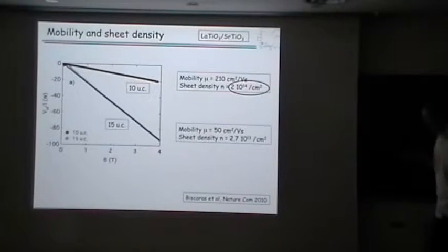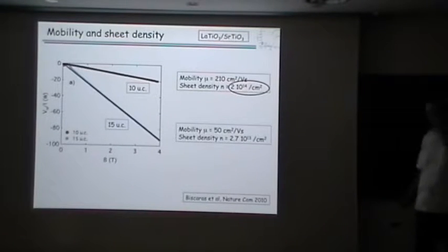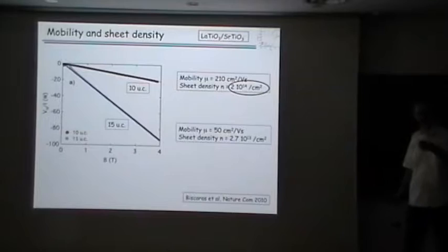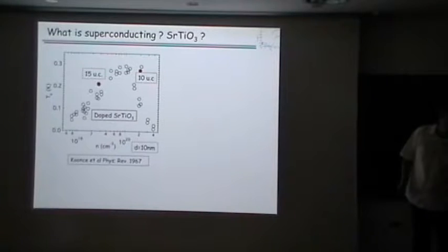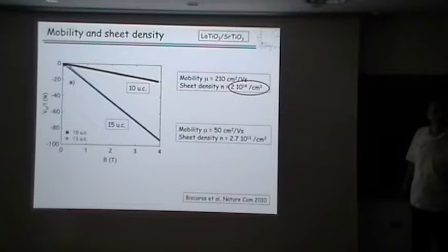So these are the first measurements we made. As I explained to you, it's difficult to trust blindly the Hall effect to give the number of carriers. But if you do it, you find the number I was talking about yesterday. It depends on the sample, and the best samples are around 10 unit cells in our case. And the mobility is quite modest, but those numbers cannot be taken just for granted because it depends on the history of the system, and I will try to explain to you why. Excuse me, what does the magnetoresistance look like in those samples? In a few minutes I'll tell you.